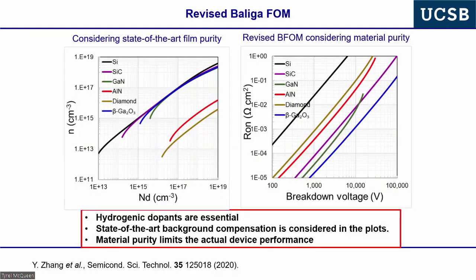But that still 60 meV actually turns out to be a fine number for silicon carbide. And when you look at the dependence of electron concentration on net doping, in these plots we compare silicon carbide, GaN, aluminum nitride, diamond, and beta gallium oxide. Here, we put a lower limit, which are these points, which are the cleanest materials that we can find in the literature. So we've actually accounted for the unintentional acceptor doping, except in the case of diamond, where this is P-type, and this corresponds to the unintentional donor doping. And aluminum nitride and diamond are actually not very clean semiconductors, even today at the state of the art. Aluminum nitride is still not very pure compared to where we are in GaN or compared to silicon carbide or silicon, okay? And same comments on diamond.